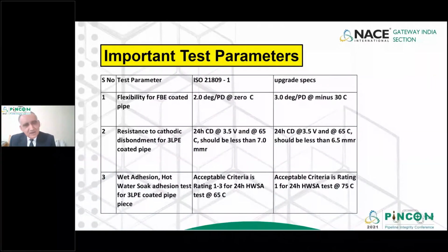Now, if we're talking of three-layer polyethylene coating, there are three most important parameters here. And why are they important? Because when these pipelines are constructed in the field, the pipeline has to be bent according to the topography or path of the line. So when it is three-layer coated, it's very difficult to find out what's happening with the FBE primer layer. So there is a new suggestion in the contractual spec that before we start the application process, we coat a few pipes only with single layer FBE and conduct some additional tests to make sure that the three-layer coated pipeline will always perform as expected. So one of the most important parameters is the flexibility test for the single layer coated pipe.